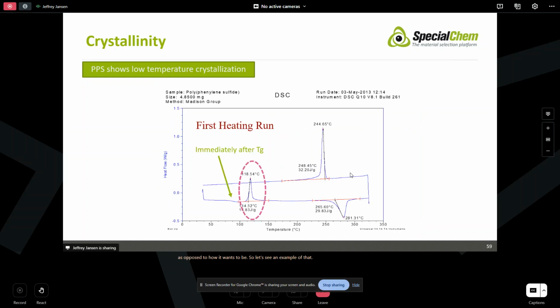So for some materials, we're going to see, as we heat the sample up, we're going to see this nice exotherm, which tells us that the material is forming crystals during the actual DSC run itself. This is a polyphenylene sulfide material, PPS. You can see that immediately after we go through the glass transition, that's right here.